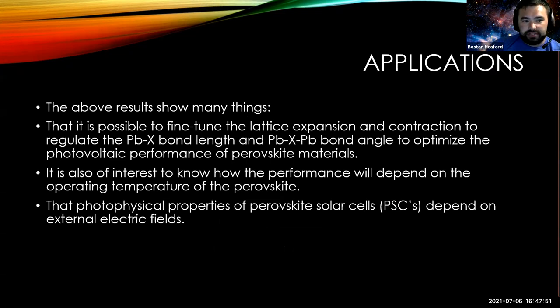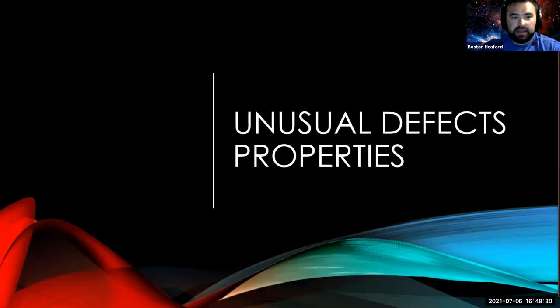And so the above results show many things: that it's possible to fine tune the lattice expansion and contraction to regulate bond lengths and angles to optimize photovoltaic performance of perovskites. It's also interesting to note how the performance will depend on the temperature of the perovskite if you're putting it in a hotter place or cold place. And that some of the photophysical properties will depend on external electric fields. So you can use all these things to fine tune the performance of the solar cell, at least in those applications. And so that was the first section.